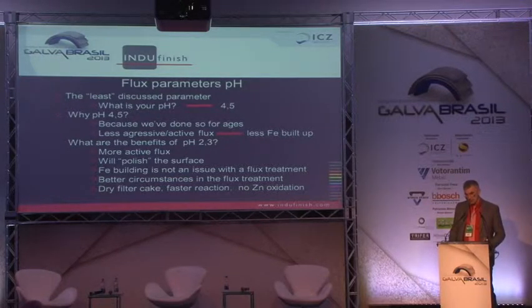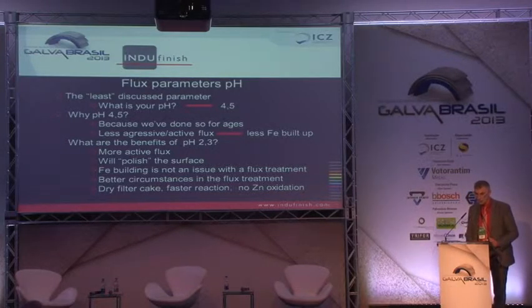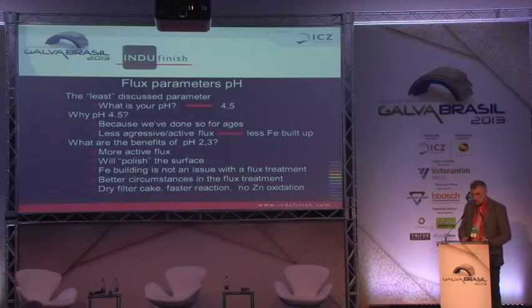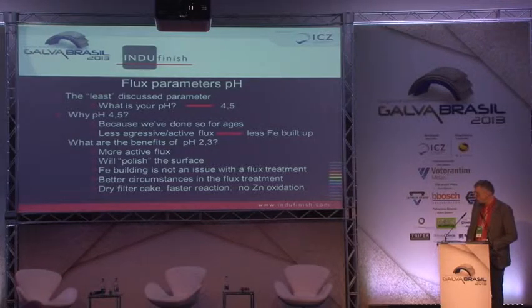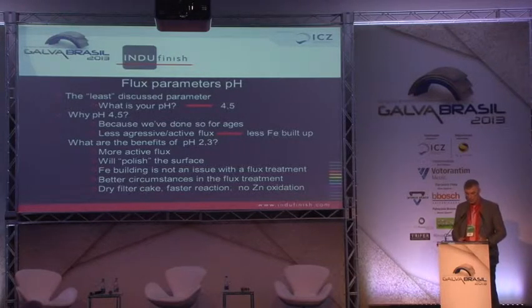But if something goes wrong, when something is not on the spot, you will want your flux at pH 2.3, because we are working with flux at pH 2.3. It will polish the surface. It's a sort of slight pickling, a slight last step in pre-treatment. A disadvantage is that your iron content will build up faster in the flux tank. But if you're using our unit, we will take the iron out, so no problem.